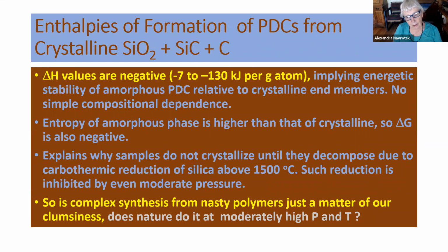The biggest surprise early on in our first set of projects was that we found that if one looked at the energetic stability of the polymer-derived ceramic relative to its components, which would be SiO2, and it doesn't much matter whether you take quartz, cristobalite, or silica glass, plus silicon carbide plus carbon. If you take those as starting materials and you ask what is the energetics of formation of the polymer-derived ceramics from these, our early calorimetric studies showed that these reactions were actually exothermic. The formation of the polymer-derived ceramic from these end members was stabilizing. Furthermore, because the polymer-derived ceramic contains significant amount of disorder, it's almost certainly of higher entropy than the starting materials, so that makes it even more stable.